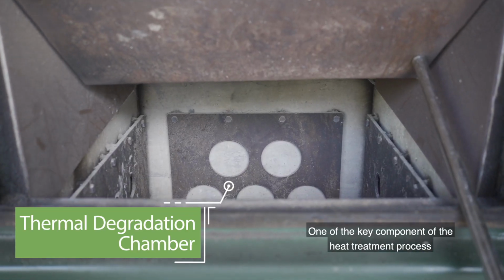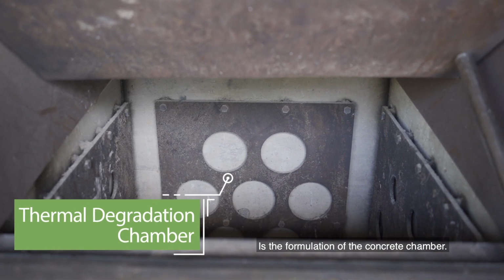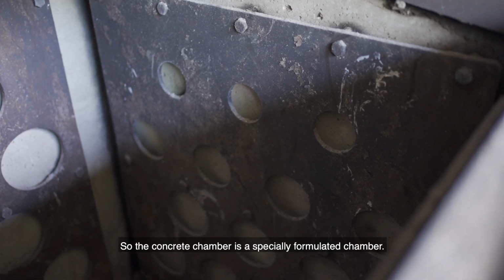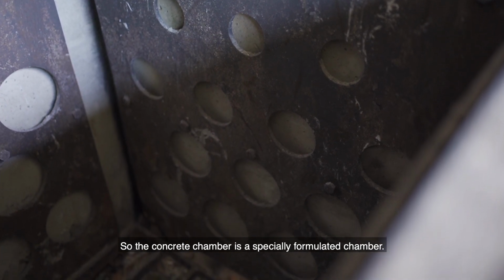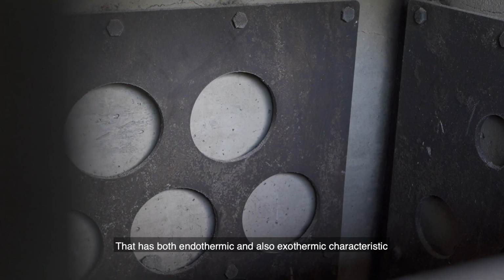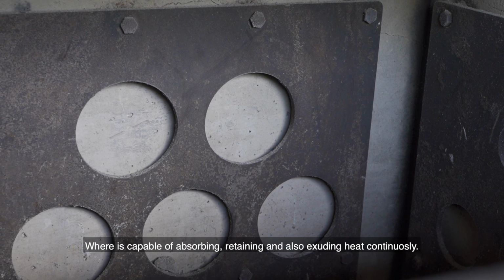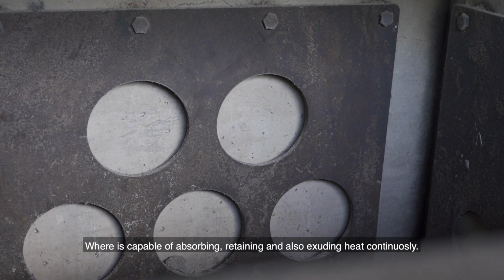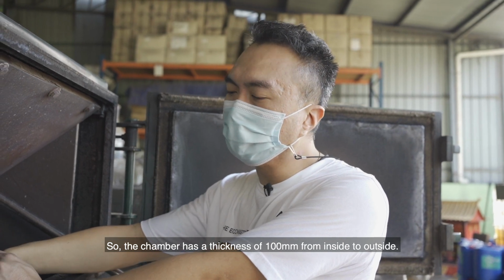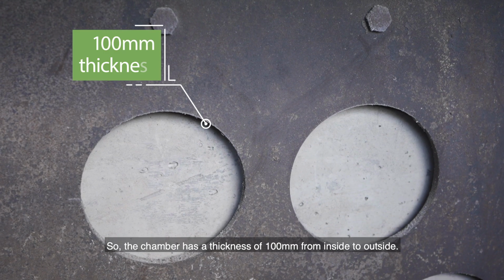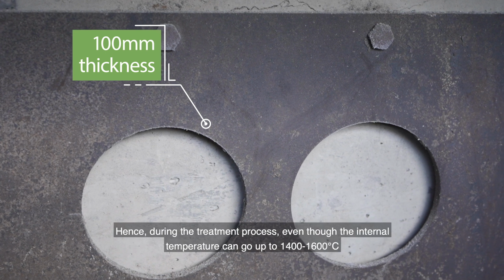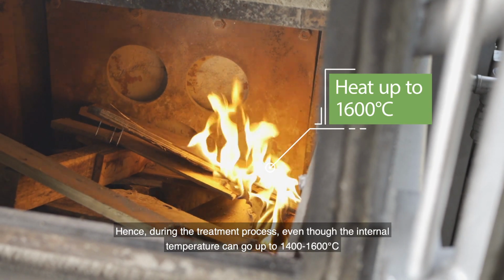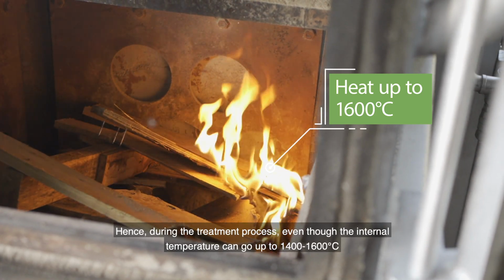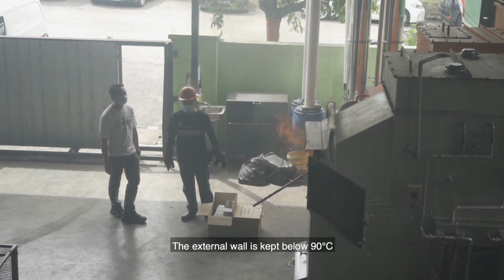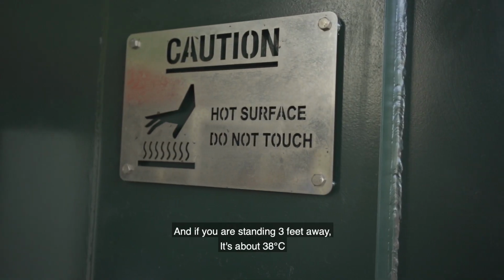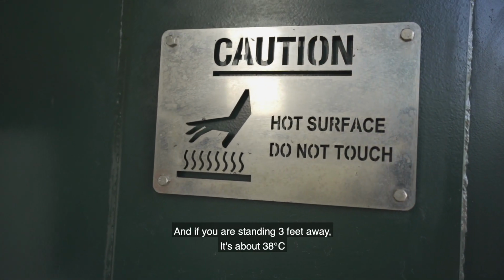Okay, one of the key components of the heat treatment process is the formulation of the concrete chamber. So the refractory concrete chamber is a specially formulated chamber that has both endothermic and exothermic characteristics, where it's capable of absorbing, retaining, and exuding heat continuously. The refractory chamber has a thickness of 100 mm from inside to outside. Hence, during the treatment process, even though the internal temperature can go up to 1,400, 1,600 degrees C, the external wall is kept below 90 degrees C, and if you're standing 3 feet away, it's about 38 degrees C.